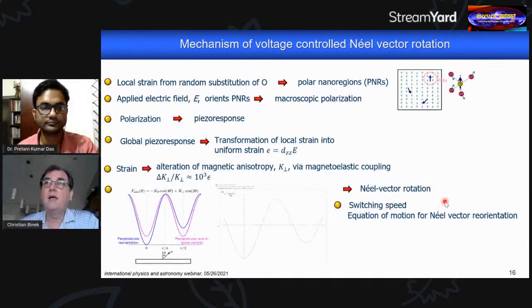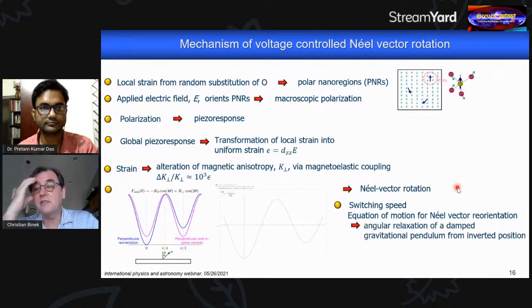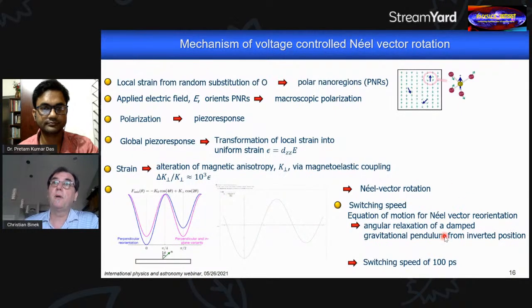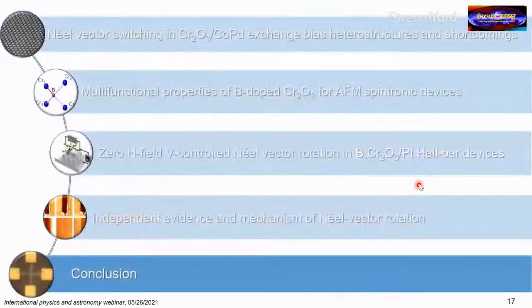Now, the final remark is about switching speed. I do not have the experimental results yet, which would be extremely exciting, of course, but we have collaboration with theorists, and they were able to map the switching of an antiferromagnet onto a mechanical analogy, an inverted gravitational pendulum, and by punching in the material parameters, they estimated that a switching speed of 100 picoseconds should be possible, which would be quite an advantage over ferromagnetic spintronic devices, and is indeed interesting for memory and energy efficient, non-volatile, scalable memory. So kind of what everyone wants in this context.